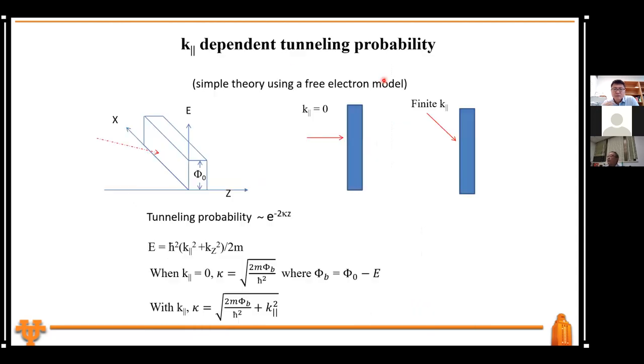And let me go ahead and skip this one and ask, well, why is that so? When we do tunneling spectroscopy, we usually think of the tunneling probability as having an exponential dependence on the so-called decay constant, kappa, times the tip-to-sample distance. Typically this decay constant is proportional to the square root of the barrier height. But this is true only if you don't have parallel momentum. I will use the free electron model first as an illustration, because most of the time that's easier for a student to understand.